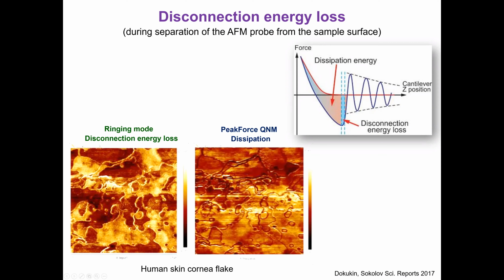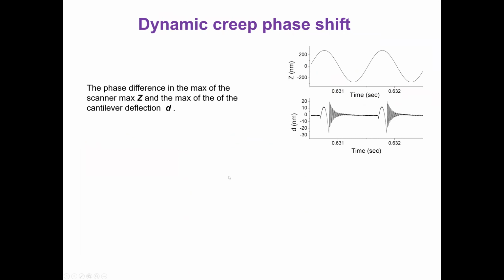So this is an example of dissipation in PeakForce QNM, and disconnection energy losses. And you can see that on a human cornea flake, you can more clearly see flakes, and surprisingly there are fewer of these line artifacts. These are again recorded simultaneously. So it actually means that both channels give you slightly different information, so they are sort of complementary. It's pretty interesting.